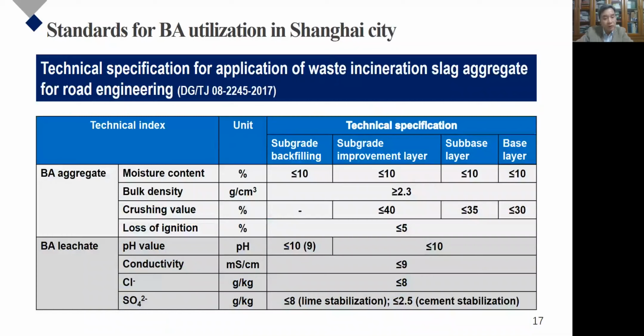For example, in Shanghai city, a local standard was issued in the year 2017, which addresses the technical specification for application of bottom ash aggregate for road engineering. The different usages, including subgrade backfilling, improvement layer, subbase layer, and the base layer, are considered. Besides moisture content, bulk density, and crushing value, the soluble salt of chloride and sulfate, leachate pH, and conductivity are also regulated.